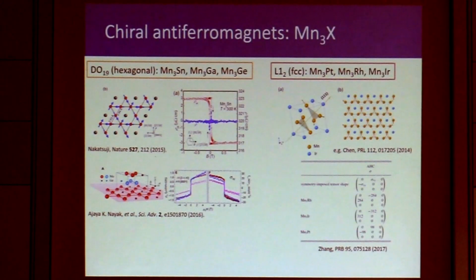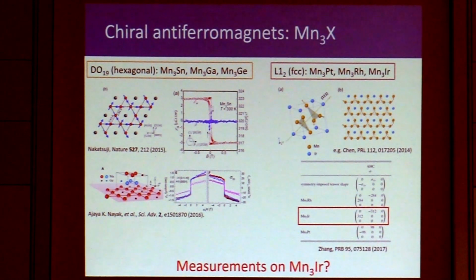Okay. So the third topic is about chiral antiferromagnets. We recently made an effort to make thin film chiral antiferromagnets, manganese 3X. Manganese 3X has two groups. One is hexagonal, and the other one is FCC. The most studied one is the hexagonal, like manganese tin, manganese gallium. But the FCC type is less studied. In fact, theoretically, manganese 3 iridium has the highest anomalous Hall conductivity, but there's no experimental report. So we just try this material.